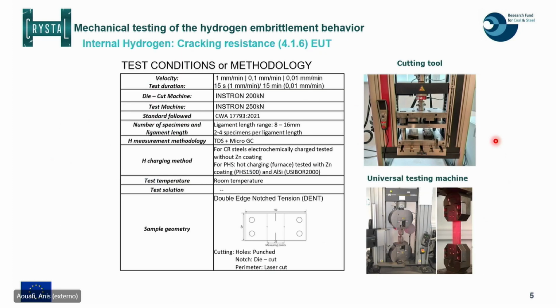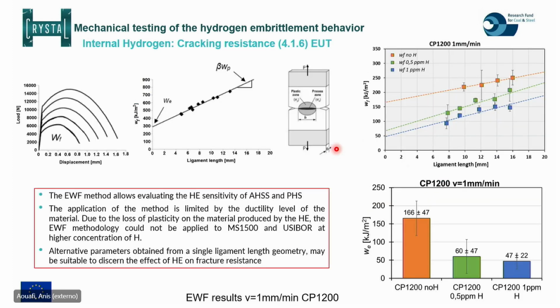The second result that we have chosen to show you today makes the bridge with what has been presented this morning, and applies the essential work of fracture methodology to the hydrogen embrittlement topic. So the principle of the test, I think the details have been mentioned this morning. The specimen is a double notch specimen, and they have been used on specimens that were electrochemically charged for cold rolled steel or hot charged for press hardened steel, and different strain rates or velocities have been used for this test. So the results that have been obtained, and here I will focus only on the case of CP1200.